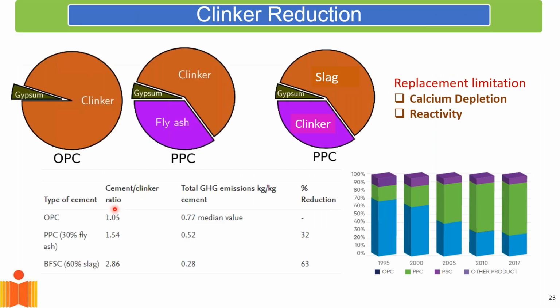And that has given rise to the production of these blended cements. So if you look at OPC, this is typically clinker 95% and gypsum about 5%. Today, we are producing blended cements in the form of PPC, where I have clinker and fly ash to the tune of 30% and gypsum 5%. So basically, my clinker factor is already decreased.